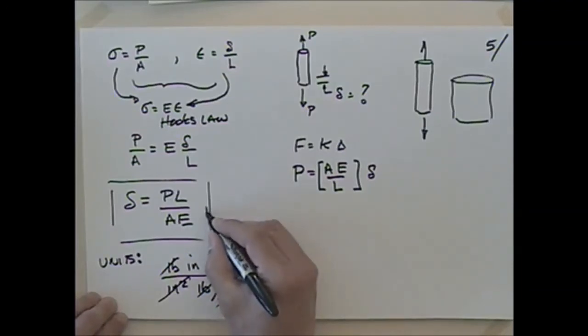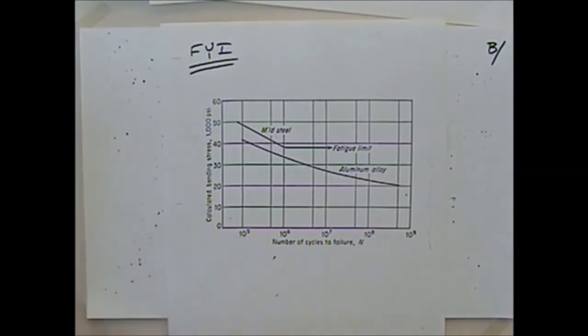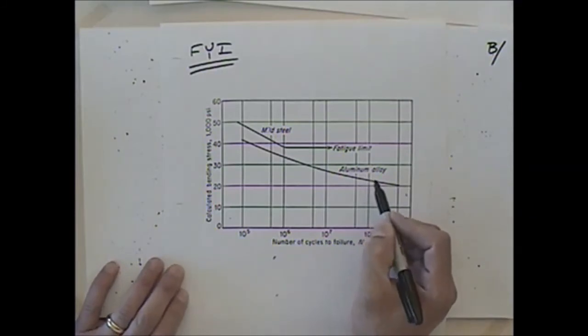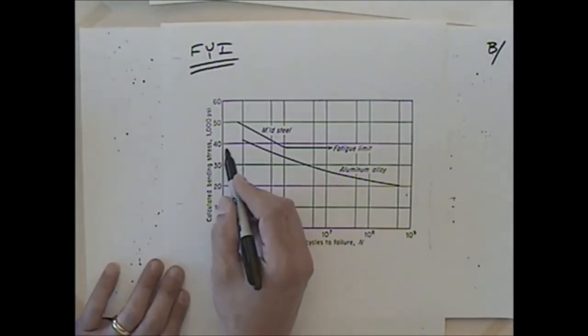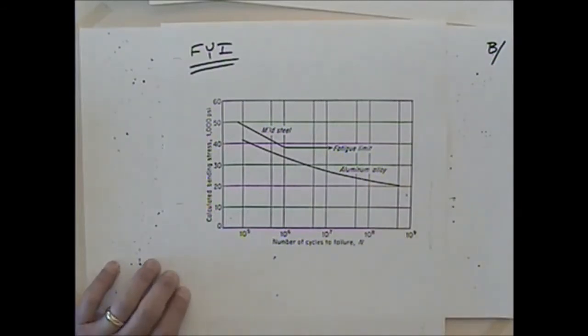We will come back next time and look at the implications of that equation. One interesting thing to show before we finish is this graph about fatigue. Aluminum has no fatigue limit, whereas mild steel does have a fatigue limit. As long as you keep your stresses under about 40,000 PSI for mild steel, you can cycle the load as much as you want and it won't fatigue.